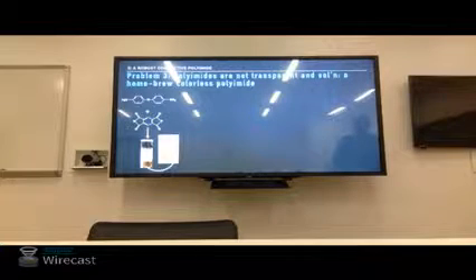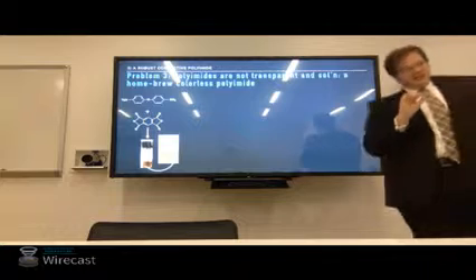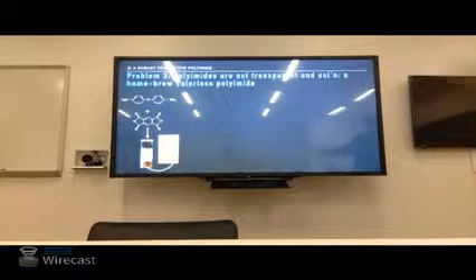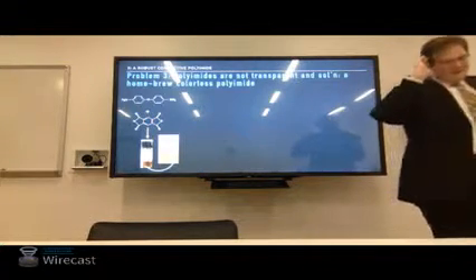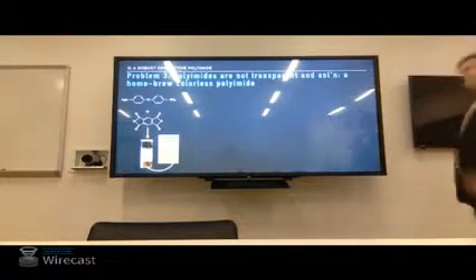So what we end up having is something more in the tens of micron layer, where this becomes unacceptable in transmission. True, if I just wanted to encapsulate the wires and just wanted that one layer, yeah, you could definitely get away with Kapton, because the absorption is going to be negligible in 100 nanometers. However, then the next layer next to the Kapton has to step down or index match and things like that. We just have a nesting doll problem. So we're going to say, let's have our electrode be impregnated right into our substrate.